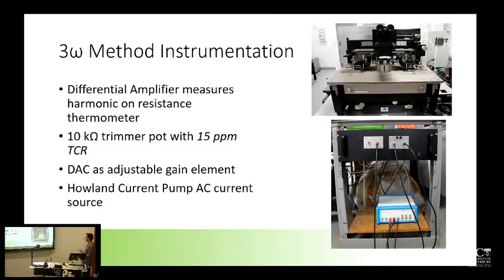So this is some instrumentation. Up here we've got the probe station, which is a temperature controlled electronics probe station, which can range from about negative 65 degrees Celsius all the way up to 200 degrees Celsius. So I can probe in there and then take the temperature up and down and measure the thermal conductivity, changing the temperature. I've got some differential amplifiers in there, a 10K trimmer pot with a really low TCR, so it doesn't interfere with any of the other 3 Omega signals that I'm getting out.